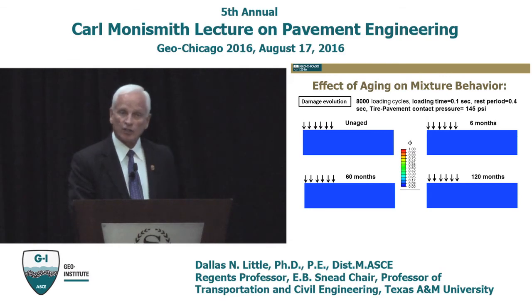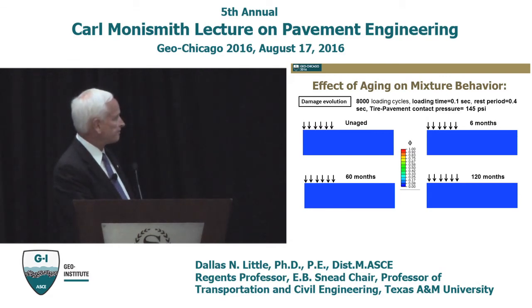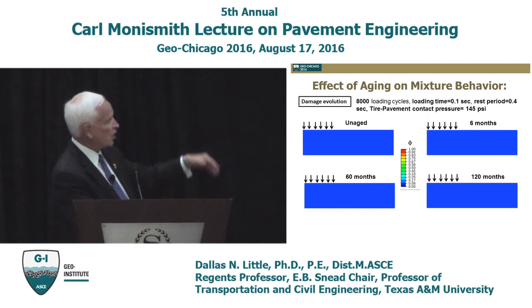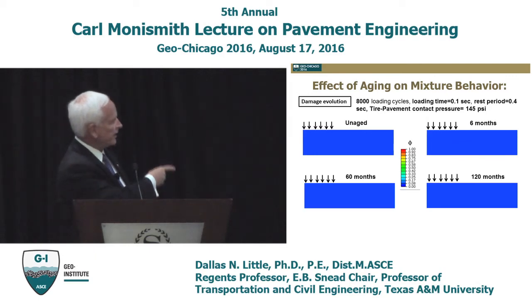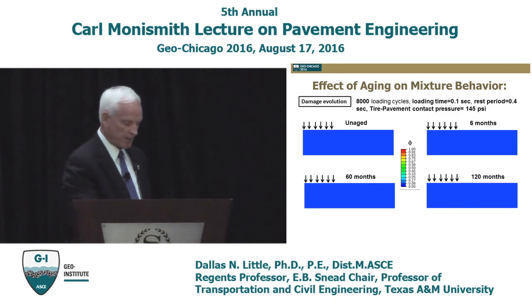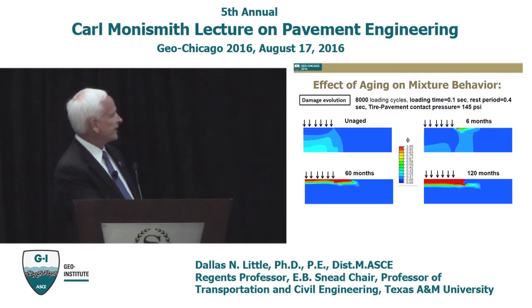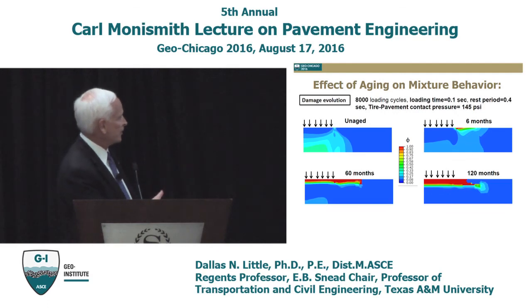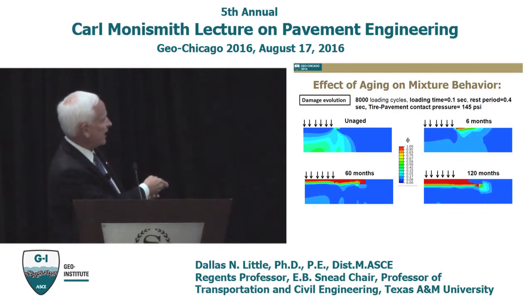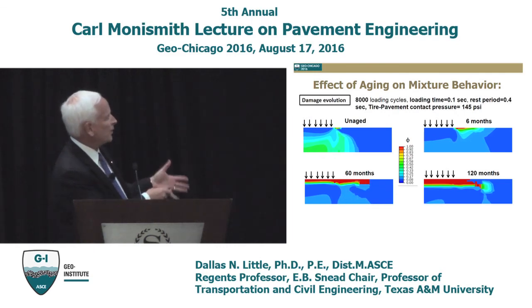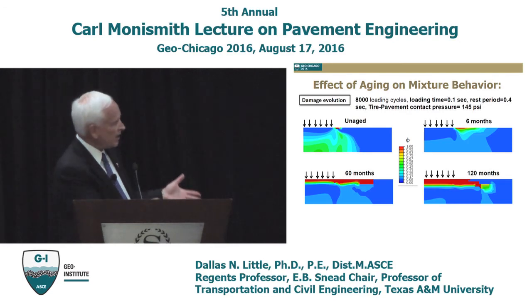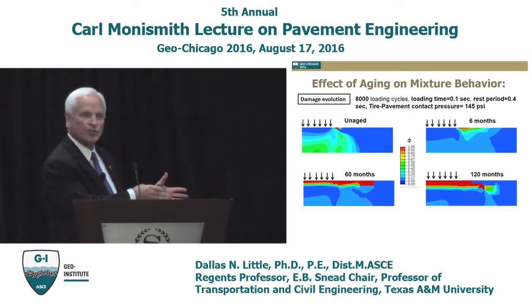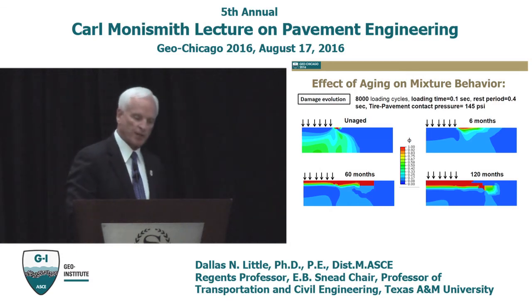Now this is another localization model. In this particular case, what we've got is 4 asphalt segments. We've got a load under the arrows. We've got an unaged on the left upper, a 6 months on the right upper, and then a 60-month lower left, 120-month lower right. And we look at the evolution of damage. This is 8,000 load cycles, and you can see another change in the localization of damage. If it's unaged, not as much damage, but it's still localizing near the bottom, and with the effect of the aging, as you would expect, it becomes more brittle, but the critical area is near the surface, and it expands as the aging process occurs.